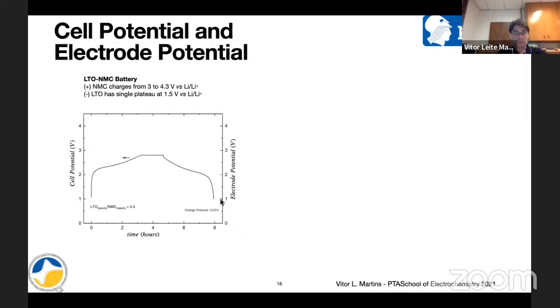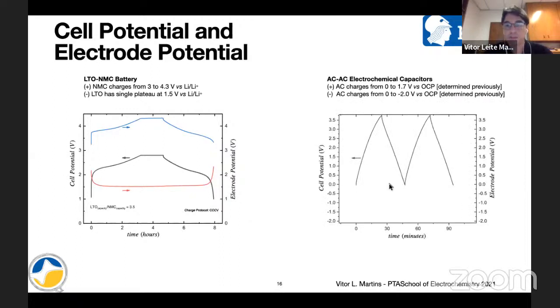But what is actually happening is that we have 2 electrodes in the cell that are experiencing 2 different reactions, right? So the cell potential is this black line here. And then we have the blue line of the positive electrode and the red line of the negative electrode, right? So this is for a battery. So the cell potential here is the difference between the blue line and the red line. In an electrochemical capacitor, you also have the positive and the negative electrode. In this case, they are the same, activated carbon, but they are operating in a different polarization, right? So you have the positive and the negative. So this is the cell potential, but actually those are the electrode potentials, okay?